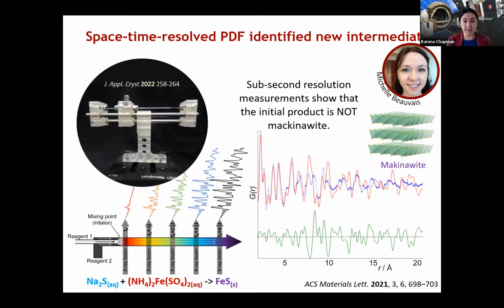Well, actually, it does look something like mackinawite, but it's definitely not mackinawite. It's got a very similar local structure—you still see the same iron-sulfur distance, the same sulfur-sulfur distance, so you've got iron sulfur tetrahedra, but we don't have the long range structure of mackinawite.